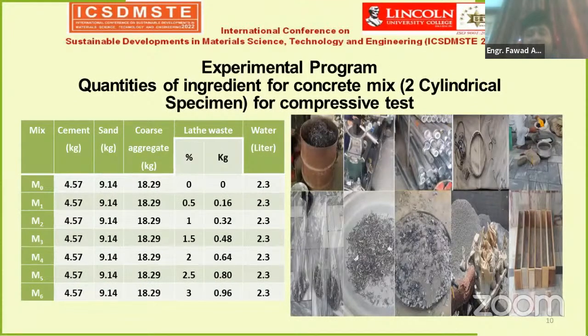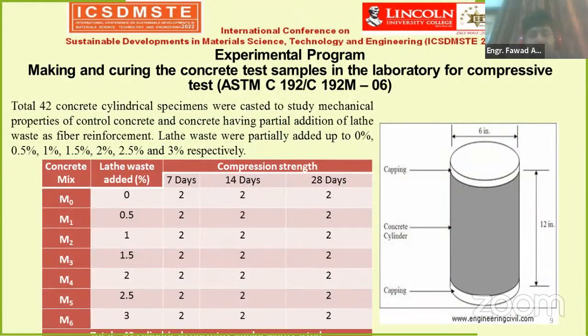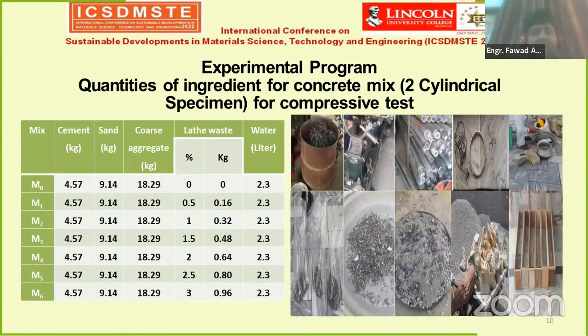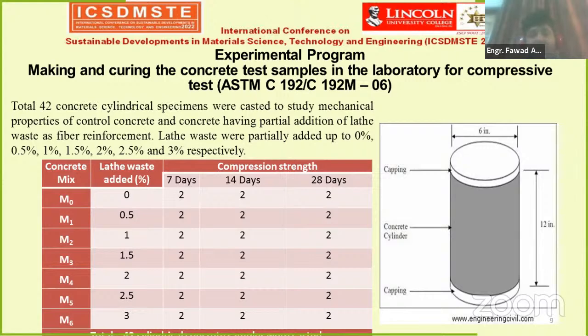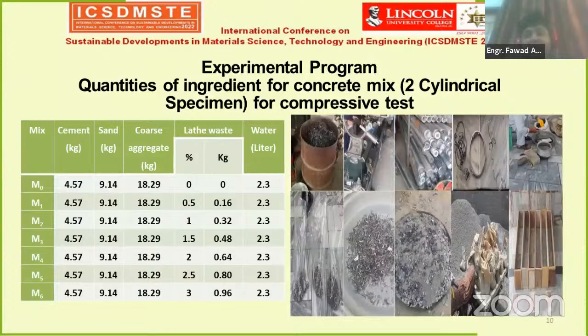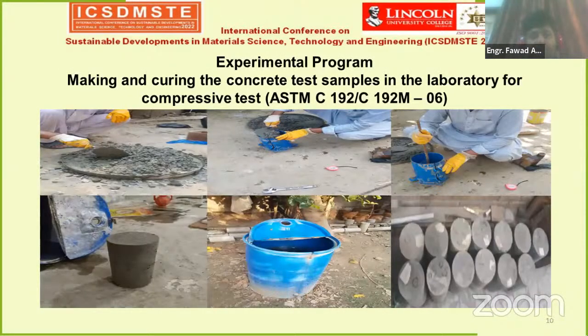Now, you can see these are the fibers which have been used in concrete, and these are the cast iron pipes during lathing. The waste was generated, and that waste has been used in concrete. As I told in previous slides, 2 cylindrical specimens were casted for the compressive test. I will go back to my previous slide. Each 2 companion cylinders were tested for compression. These are the quantities of ingredients for casting the cylindrical specimens, and American standards were followed for casting and preparation of test specimens. These are some pictures which I have taken.